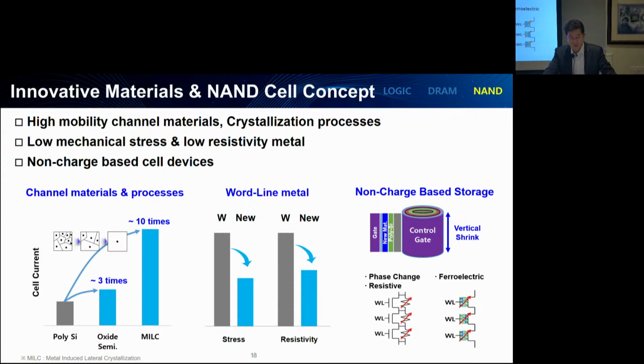To tackle the issue of low cell current, there are 2 approaches. First is grain engineering. With recrystallization processes such as MILC, metal-induced lateral crystallization, we can increase the grain size of channel polysilicon, achieving a significant mobility enhancement. And second is novel oxide semiconductor channel materials, which have a higher mobility than conventional polysilicon channel. However, this comes with the challenges of controlling the memory window and ensuring the reliability.